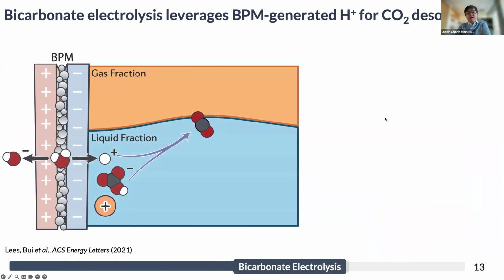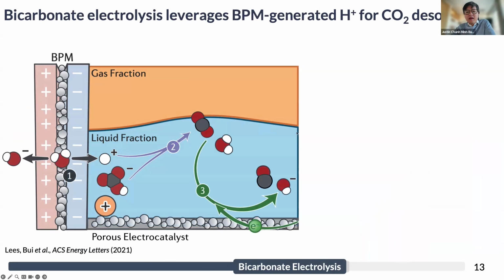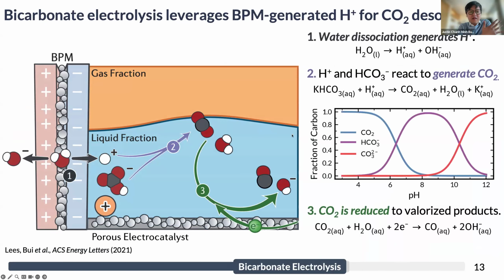The last story I'm going to talk about is this work I did on bicarbonate electrolysis. So not just carbon capture, but also converting the captured carbon into something valuable. And so this process basically relies on a lot of the principles that I talked about before. You have this acid that liberates the CO2 from our carbonate solution. But what we do here is instead of just letting that CO2 off gas and capturing it there, we put an electrode directly next to the surface of that bipolar membrane that contains a silver catalyst. And so when we liberate the CO2, that CO2 reacts directly at the catalyst and forms syngas, a very value-added industrial product.